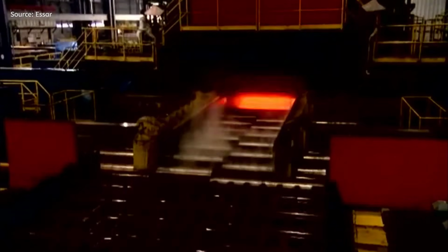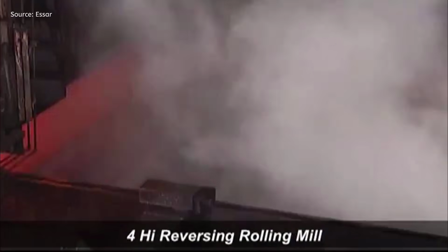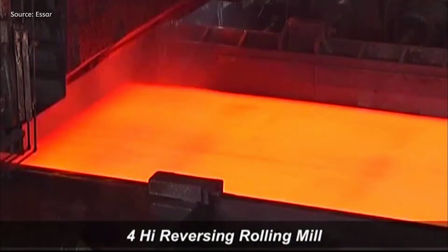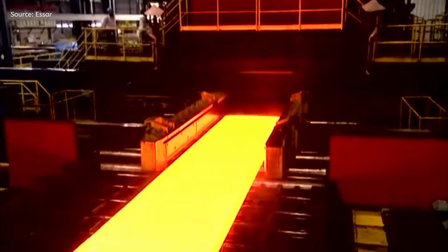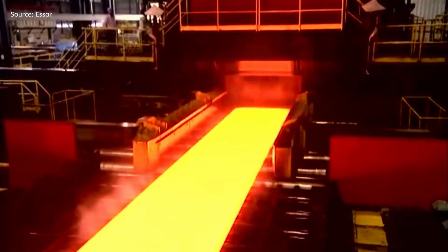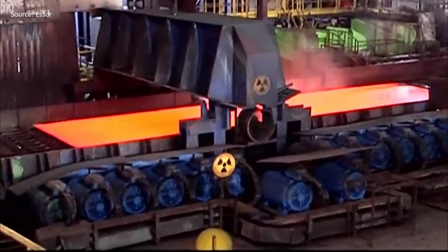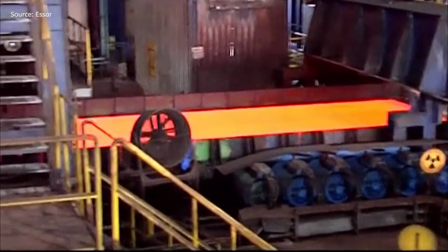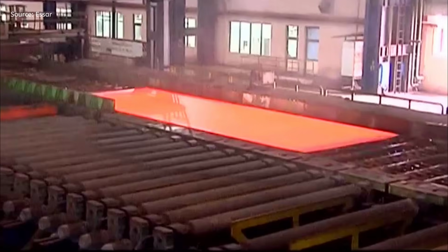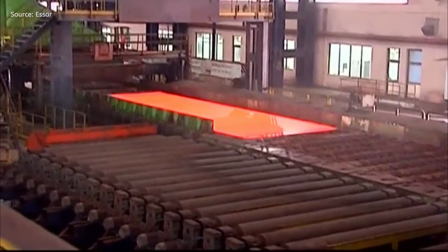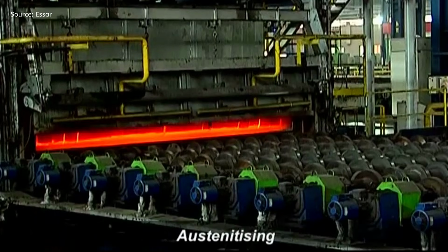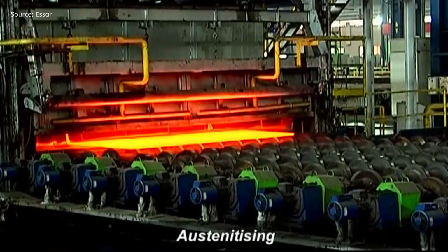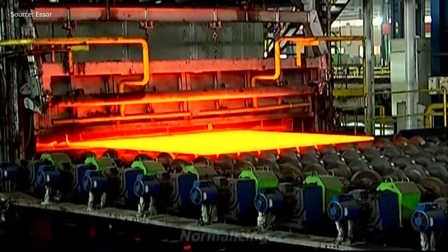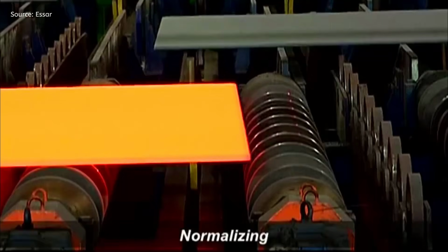The plates are further processed using thermomechanical controlled rolling with accelerated direct cooling and quenching to enhance abrasion resistance, formability, and toughness. After rolling, the plates are cut to customer specifications using universal torch cutting machinery and undergo quality checks through manual ultrasonic testing. Heat treatment facilities provide normalized, quenched, and tempered plates for specialized applications.